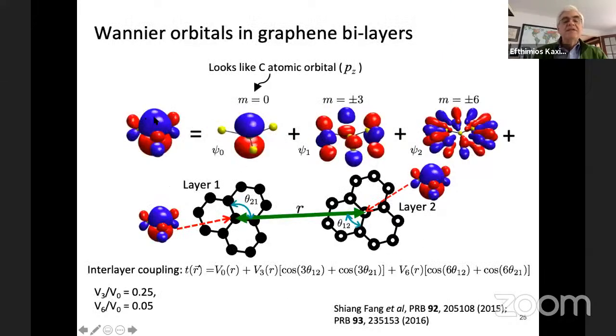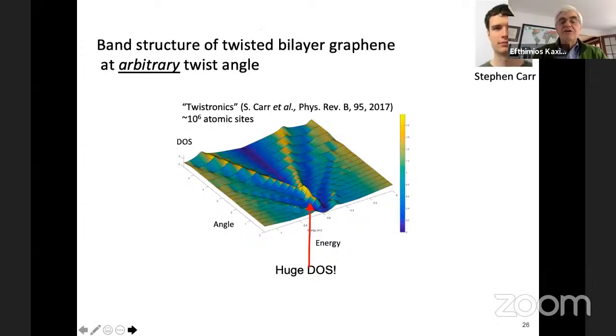So this is what the localized states look like. So this is a localized electronic state on a single atom, and you can analyze it in sort of higher harmonics. And then you put each one of these localized states in each atom on the bottom layer and a corresponding state on each atom at the top layer, layers one and two, and allow those local states to interact to produce essentially the same physics with the same accuracy as the first, the ab initio calculations. So then we were able to do calculations for very large systems containing of order millions of atoms as these periodic cells at a large scale require.